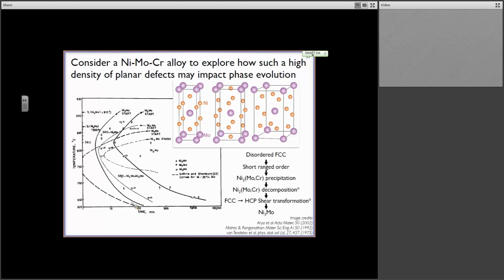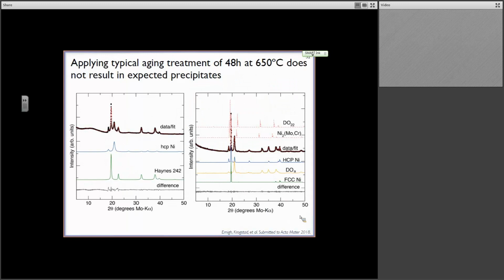Now, if we leave this in service for a very, very long time, or we are just trying to study it, and we extend this at the same temperature, we get out to hundreds of thousands of hours before ultimately we get down here to the equilibrium structure. And so you can see that there are many steps in between here necessary to finally get here. And if you actually do start to see this equilibrium structure in your microstructure, it's a bad thing. The mechanical properties have suffered. This would be considered overaged. But you want to know when that's going to happen, and so you need to understand all these bits in the middle to make sure that it hasn't started to happen in your alloy in service.